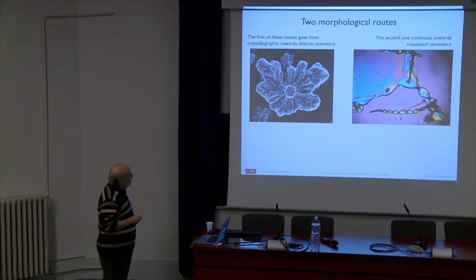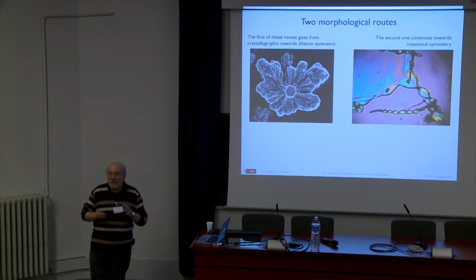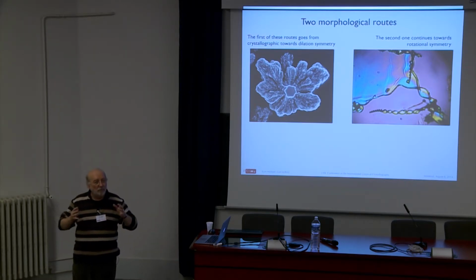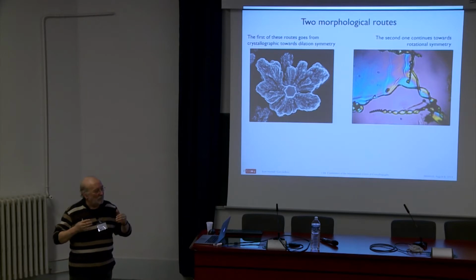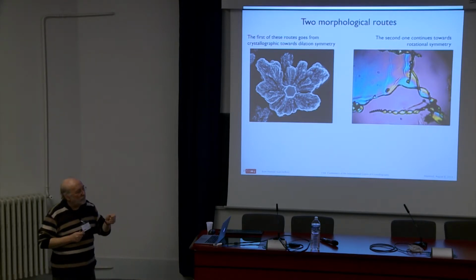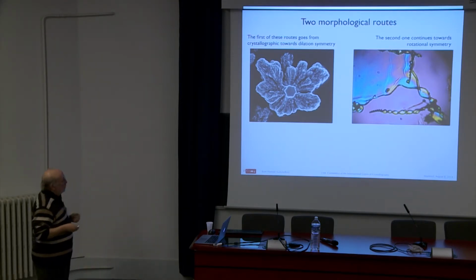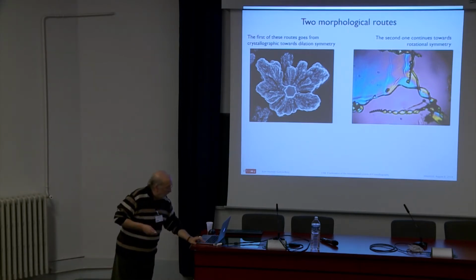The starting point is always a crystal of the carbonate with pseudo-hexagonal symmetry. Okay, so these have the internal structure of a single crystal, and if you maintain this, nothing will happen because you will grow the crystal, and the crystal will always have a faceted shape. So it's critical to break this symmetry, and this is what the impurity, I mean the silica, does. How does silica do that? Well,